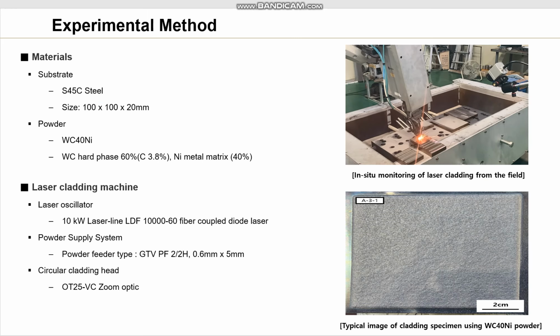Okay, in this study, S45C steel was used as the substrate material, that is to say base material. The chemical composition and mechanical properties are similar to rolls in the continuous casting, and the cost is cheaper than existing base materials such as SCM440. The size of the specimen was set to 100 mm in width and height and 20 mm in thickness.